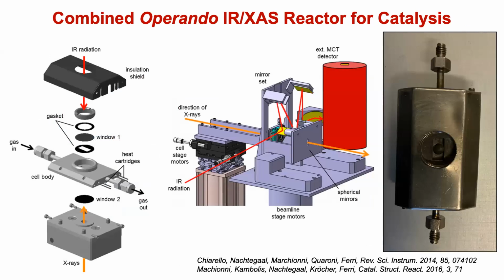Here you see the cell on the left. The whole point is that it has a low dead volume. The advantage of this low dead volume is that you can do transient experiments, because you can easily switch gases from A to B and back. On the right, you see the cell with all the details, the X-rays coming in. On the left image, you see the orange X-ray beam going in, and the top red infrared beam coming in from the top.